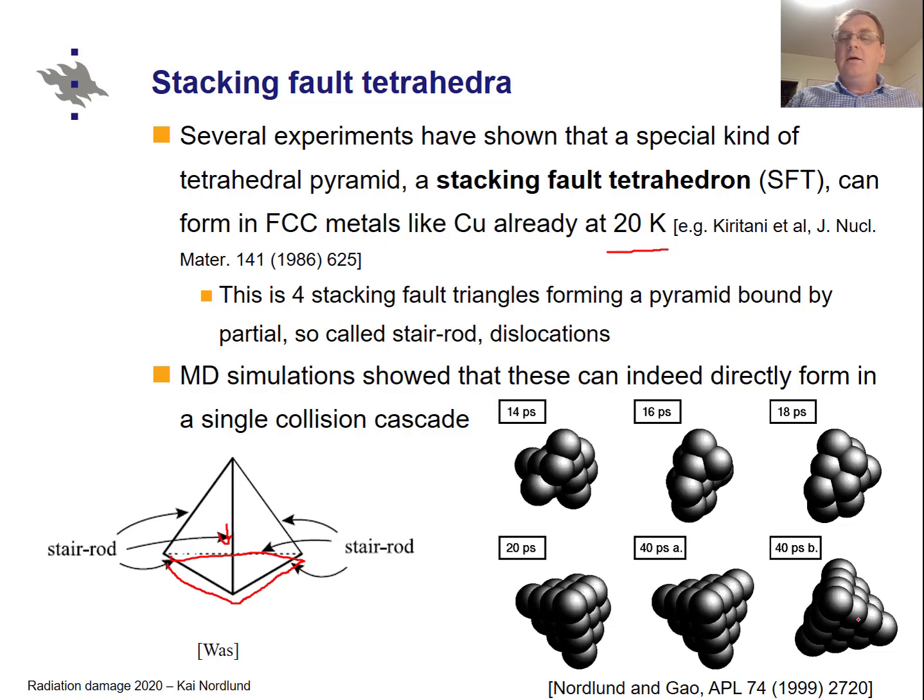But anyway, it seems that sometimes you indeed observe in MD simulations the formation of stacking fault tetrahedra. This was a simulation in copper where one saw perfect stacking fault tetrahedra. This is analyzed in terms of the vacancies, so you see the vacancies which are surrounding this tetrahedron.